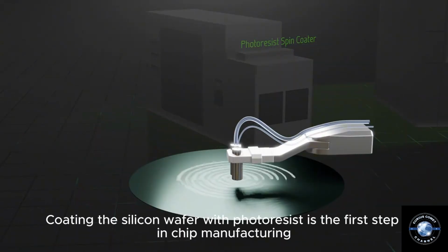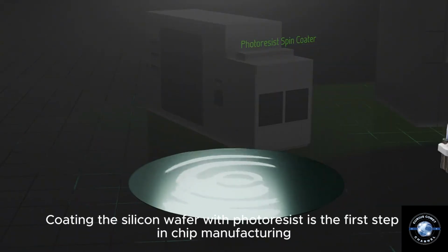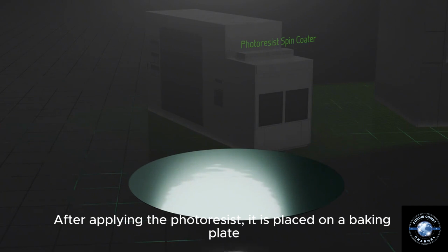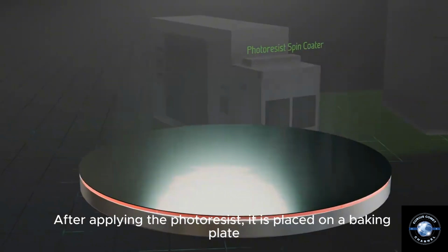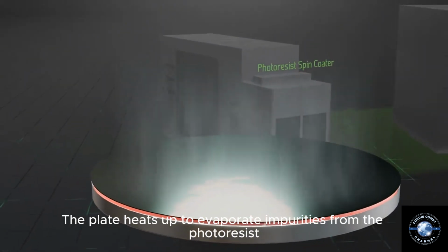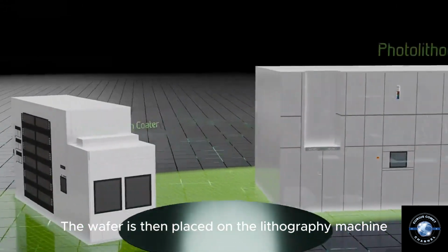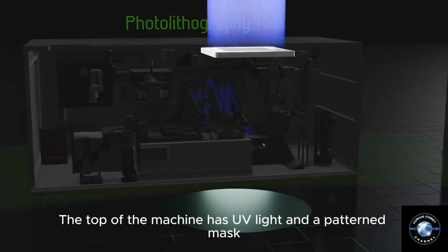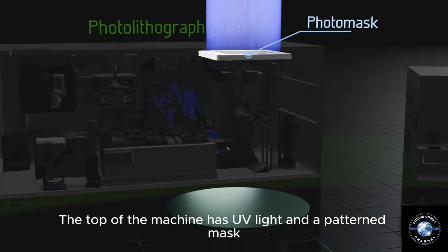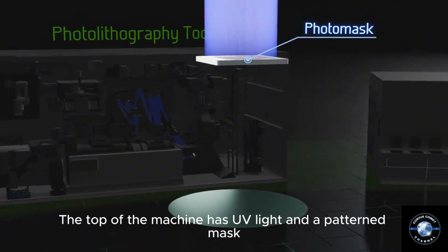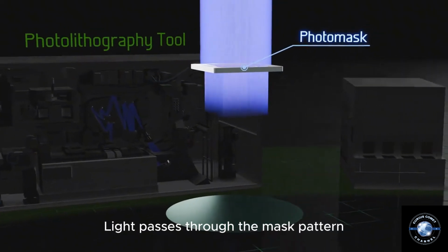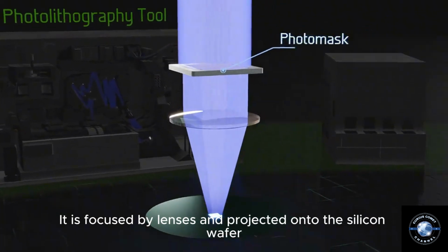Coating the silicon wafer with photoresist is the first step in chip manufacturing. After applying the photoresist, it is placed on a baking plate. The plate heats up to evaporate impurities from the photoresist. The wafer is then placed on the lithography machine. The top of the machine has UV light and a patterned mask. Light passes through the mask pattern. It is focused by lenses and projected onto the silicon wafer.